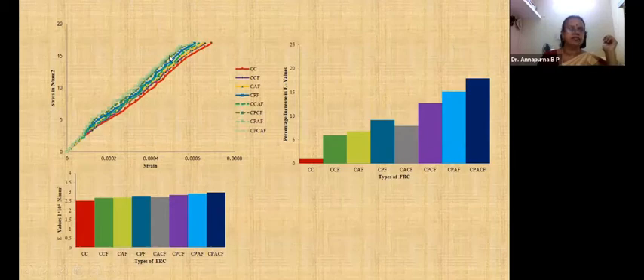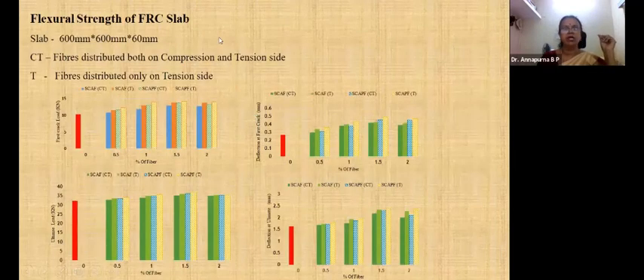Then the flexural strength, now this is for a slab also. We have tested a slab of size 600 by 600 by 60 mm using these fibers, and it is seen that the fibers contribute much more to the first crack load than to the ultimate load. So here for the first crack load, this is the fibers, that is CT, and we have also worked on fiber distributed on both compression and tension sides, that means all over the slab, and here the fibers are distributed only on the tension side.